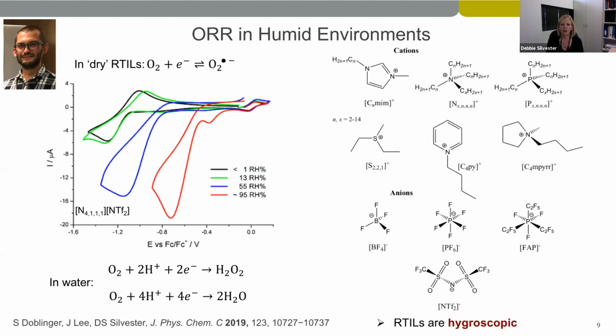We know that ionic liquids have many different structures, and they also take in different amounts of water. So we decided to look at the effect of changing the cation and the anion structure and how this affects the oxygen reduction reaction over a range of humidities. We have a wide range of cations here: the imidazoliums, and particularly this tetraalkyl phosphonium with long chains, which is the most hydrophobic cation. And then we also change the anions. We have the more hydrophilic anions, the tetrafluoroborate and hexafluorophosphate, and then we move to our NTF2 and FAP hydrophobic ions.